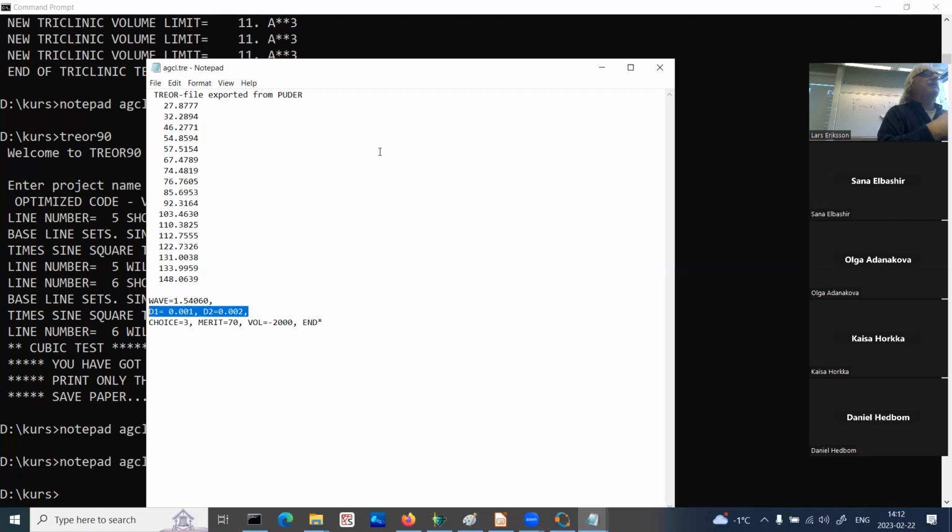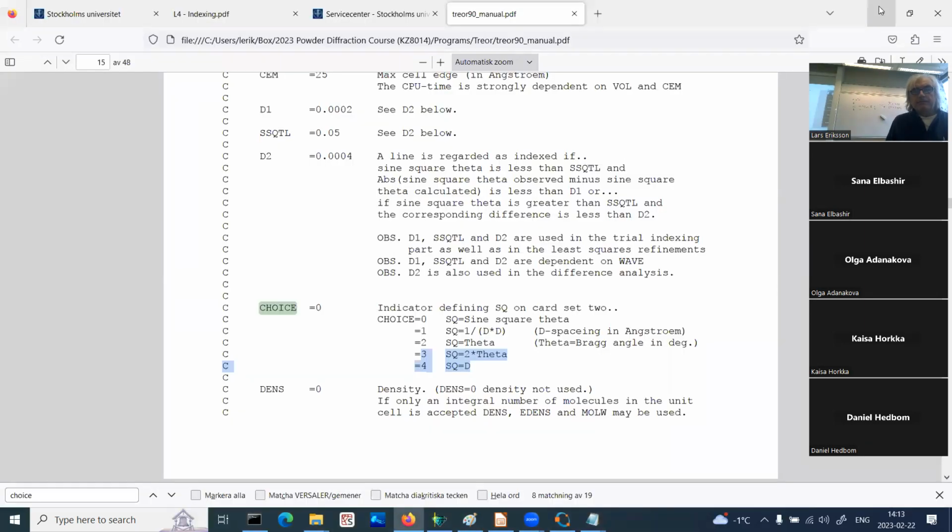It would have been better. I haven't done that yet, but I will do that before I die: to synthesize a lot of silver chloride and record it in back-loaded, because then the systematic errors would be more or less absent. We don't have any good way to actually deal with the systematic errors in Treor90.